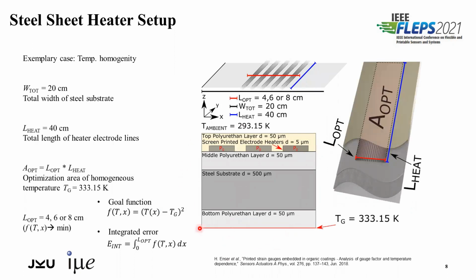This slide here shows the steel sheet heater setup. It should demonstrate the possibility of the design for a precise temperature profile. And as an example, we use a uniform temperature profile. What do we have? We have a steel substrate here with width W total embedded in a polyurethane insulation. And on top of one insulation layer, we have screen printed silver electrode lines with length L heat, which are again covered by an insulation top layer. And the temperature inside this optimization area here should be homogeneous. And our goal temperature in this area is 333 Kelvin or 60 degrees Celsius. And this is measured at the bottom of the stack.